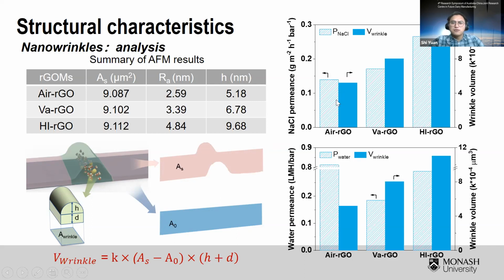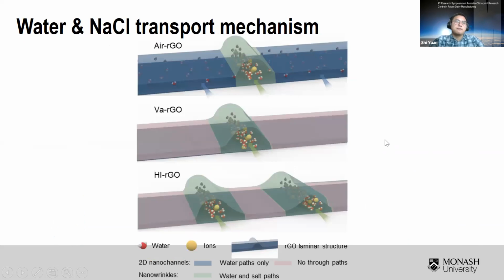And by comparing the wrinkle volume with the sodium chloride permeation rate, we confirm that the salt will only transfer in the nanowrinkle freely, while water can go through membranes in 2D nanochannels like in here, when the interspace is large enough. So we propose a new mass transport mechanism in RGOMs.